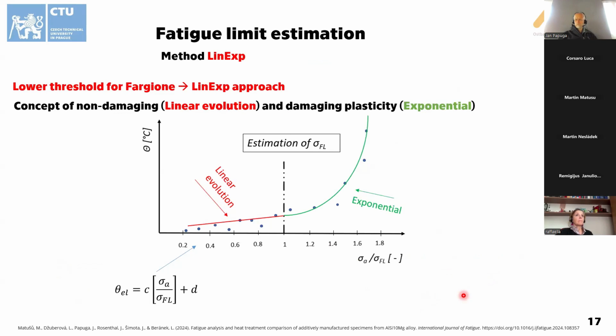What we were trying to do is not use a power law or a bilinear evolution, as we couldn't fit the data as we wanted to find a good result out of it. So we made a different approach. What we tried was to set the first part of the evolution as the evolution of the stabilized temperature related to the amplitude of load, here divided by the fatigue limit, so you can see that there is a visible transition, although this is not going to happen that easily.